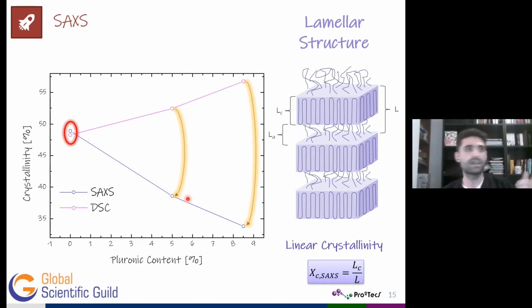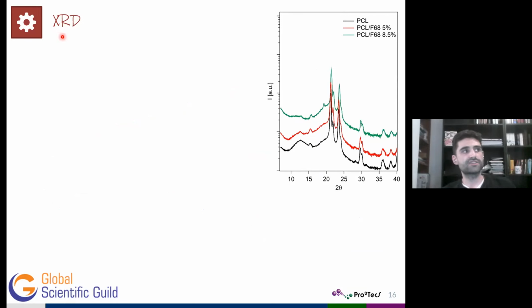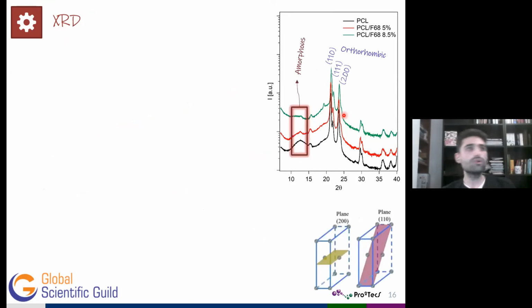Well, in order to obtain not only a qualitative but also somehow a quantitative description of those crystal morphologies, we also apply X-ray diffraction at the microscale. And as we can see from the XRD pattern, all the systems, not only the blends but also the pure PCL, the red line, the black line, exhibited the orthorhombic structure, as can be seen from the characteristic peaks corresponding to the orthorhombic unit cell. Apart from that, we also confirm the partially amorphous character of these materials from the peak located at around, I think, 12 degrees.